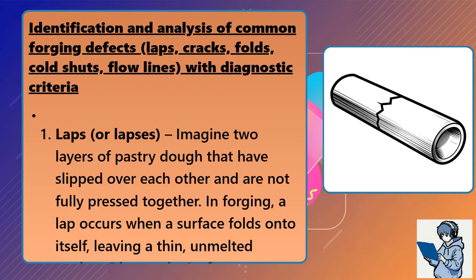First, laps or lapses: imagine two layers of pastry dough that have slipped over each other and are not fully pressed together. In forging, a lap occurs when a surface folds onto itself, leaving a thin, unmelted pocket. Diagnostic surface inspection shows a shallow trough; cross-section reveals a double layer with a clear interface.